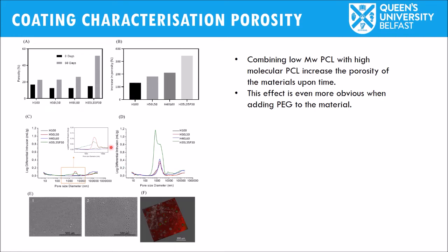It's interesting to note, for example, that the inclusion of hydrophilic fillers like polyethylene glycol in the membranes will give higher porosity, because obviously these fillers will be dissolved. This compound, polyethylene glycol, will be dissolved after a while, after 60 days in water or in an aqueous environment, and will give a higher porosity. This increase in porosity was not observed for the membranes that did not contain polyethylene glycol.